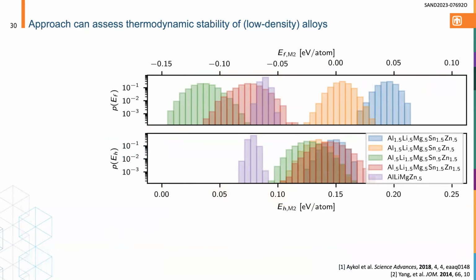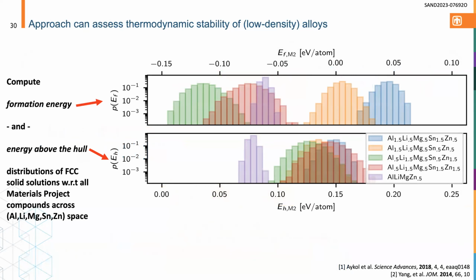Okay, so this is what I mean by that. On the top row, I'm showing the predicted formation energy distributions for a variety of compositions in this low density alloy space of aluminum, lithium, magnesium, tin, and zinc. And if you go ahead and click, Rob, what really matters for predicting alloy phase stability is the energy above the hull, or essentially, if you look at all the possible decomposition products of that particular composition, how much higher in energy is that material?